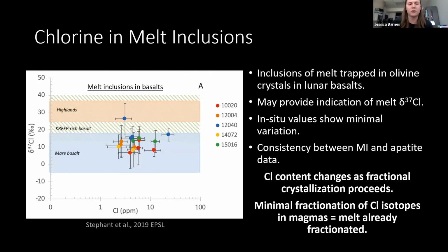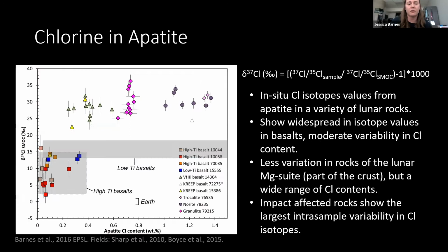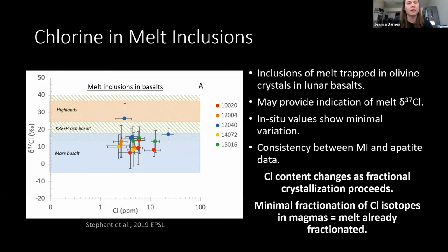Recently, in a follow-up study to the one I just showed you, Alice Stephant and colleagues at the Open University started looking at melt inclusions within some of the basaltic samples that we'd previously looked at in 2016. And one of the big questions that came out of our 2016 study was, you're looking at apatite crystals that we know form in the very last stages of, if we're looking at a basalt, the very last gasps of that basalt, that's where the apatite's going to be forming. It's a very refractory element or mineral. And so maybe what you're seeing in the chlorine isotope variation in the volcanic samples is just due to volatile loss as you're extruding that basalt to the surface, and then that lava is cooling on the surface of the moon. So to investigate that further, Alice Stephant and colleagues looked at the melt inclusions found in some of these basalts using the same instrument at the Open University.